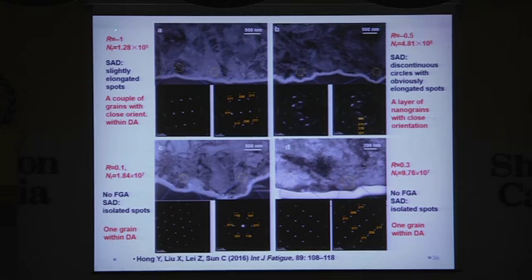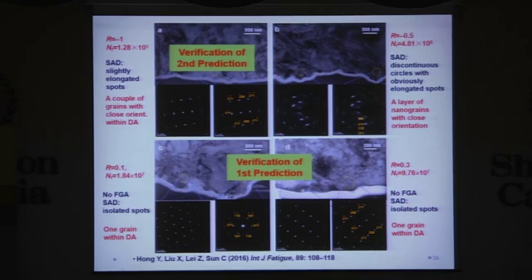This is the -1 stress ratio with relatively low loading cycles. And we see that it's a kind of slightly elongated diffraction pattern. It's a kind of texture microstructure, meaning that within this small area of SAD, there are just perhaps a couple of grains. And for -0.5, it's also elongated diffraction. But for 0.1 and 0.3 stress ratio, just underneath the fracture, in the crack initiation region, there are isolated spots. So these observations verify the first prediction, and these verify the second prediction.